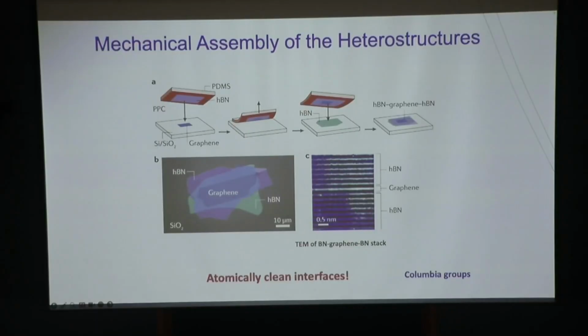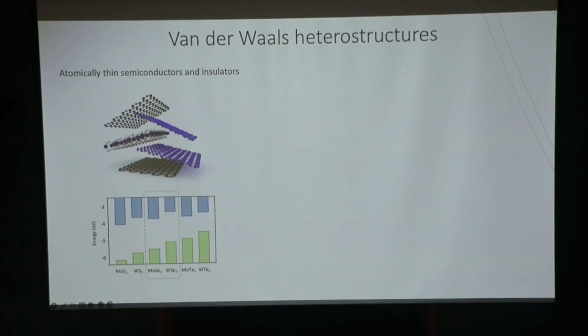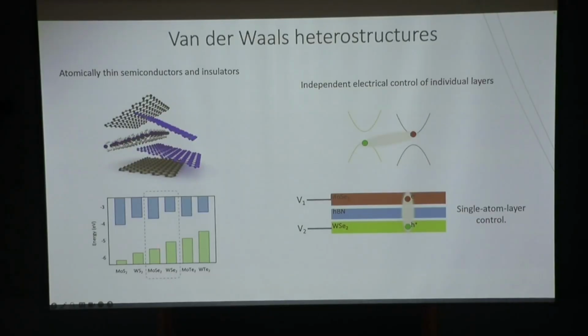But today, I will narrow down the heterostructure that we are going to play with. We focus on the electron-hole bilayer. That means we'll need two semiconductor layers that host the electrons and holes, and an insulating layer to isolate them. So we're mostly using MoSe2 and WSe2 because they have a relatively small band gap. They are relatively easy to exfoliate and work with, and the optical spectroscopy of them is also easy. So that's how we chose these two semiconductors.